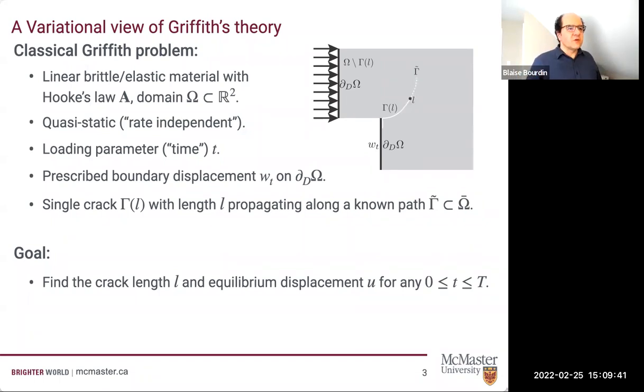And one way to think of a brittle material: if you can break something and glue it back in place, it's brittle. So ceramic is brittle, but an alloy at high temperature, which is going to have some plasticity, permanent deformation, and so on, is not a brittle material. I'm going to assume that everything happens slowly, so that's a rate-independent hypothesis, because everything happens slowly. Speeds are not really involved, but it's convenient to keep track of something that I will call time. Think of time as simply a quantity that flows only one way, and it describes that the fracture phenomena that I'm trying to describe don't depend on any velocity. But if you play a movie backward, you definitely see if something is wrong, you don't want to see pieces of the material going back to their initial configuration.